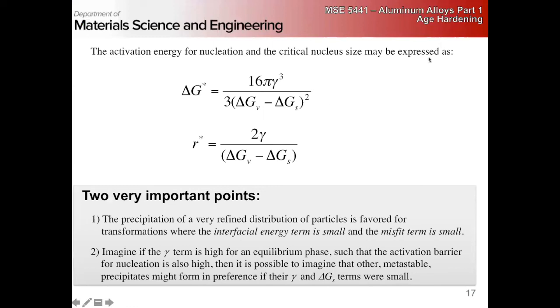So two very important points, right? The precipitation of a very refined distribution of particles is going to be favored for transformations where the interfacial energy term is small and the misfit term is small. So we can imagine if we have an equilibrium phase with a very high interfacial energy or strain term, right, we can imagine that the activation barrier for nucleation is also going to be high.